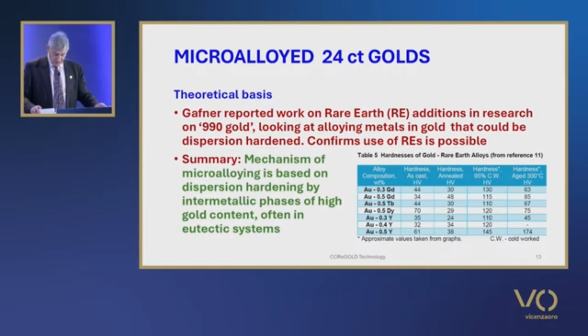Whether alloys of gold with the light rare earth metals show good properties was not known at that stage. It is difficult to comment on the results for the gold yttrium alloy, as there is no published gold yttrium phase diagram, but recent work by Ning indicates that it is similar to the heavy rare earths, with some solubility of about 2% of yttrium in gold. So to summarise, the mechanism of hardening by microalloying would appear to be based on some form of dispersion or precipitation hardening by intermetallic phases of high gold content in alloy systems that form eutectics at high gold contents, and where the microalloying addition has little solid solubility in gold.